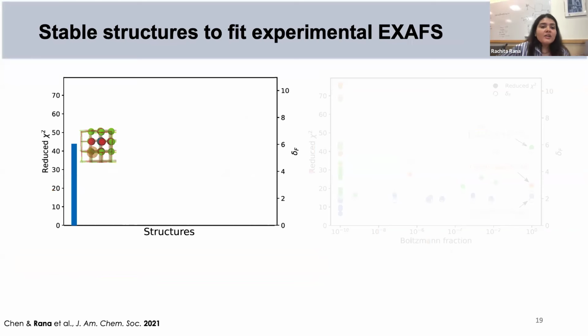So then we thought of plotting a reduced chi-square for each structure. What you see here is the bar is going to be the value of the reduced chi-square for each structure in the database. But then we also wanted to see physically what the EXAFS fit looks like. And so for that, we thought of including a delta Fréchet, which is a statistical metric for the similarity between two curves. So we were really comparing how similar the curve that came out of the model was to the